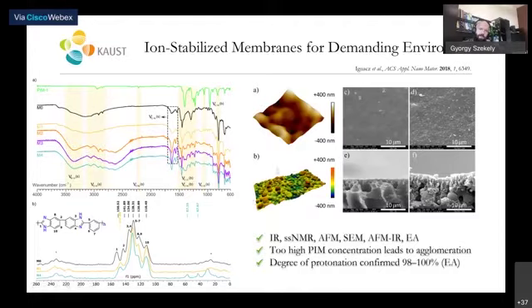And here, this image was taken with a technique called AFM-IR. Basically, these lumps represent the height of the material, and the color represents the intensity of a selected peak in IR. So what we were looking at here is whether we have a clustering of one of the polymers compared to the other one. And this image was taken at high loading of the PIM, where it actually started to aggregate and cluster. Okay, so this structure was avoided, and we couldn't go to a very high PIM content due to clustering effects.